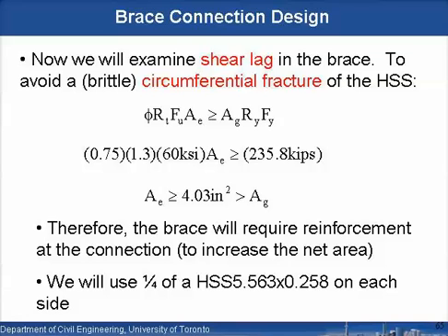So the fracture strength by this circumferential fracture mode is phi times Rt Fu Ae over here, where Ae is the effective area at that critical cross section, right at the end of the slot. And when we then put these numbers into the equation here, we see that we're actually doing a capacity check with a safety factor in here, essentially a resistance factor of 0.75, but we're multiplying by an overstrength factor for the ultimate of 1.3. This comes out to about 1 anyway, so these are essentially self-canceling, really. So we've got the ultimate strength of the brace material, 60 KSI, multiplied by the effective area at the critical cross-section, which is the fracture strength, greater than the yield strength, the yield force that's going to be developed in all likelihood in the brace.